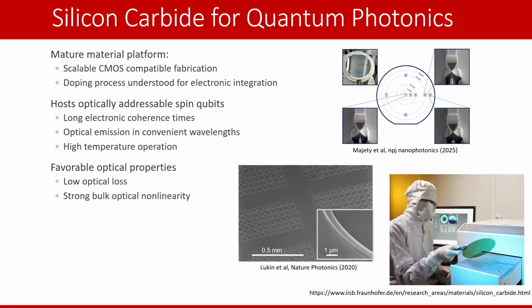And of course, silicon carbide, as a result of a lot of hard work from a lot of very intelligent people, now has excellent optical properties. It has low optical loss, on the order of less than 5 dB per meter, which is quite good, which means all of our photonics are no longer material limited. They're now nanofabrication limited. And there's also a strong bulk optical nonlinearity. I want to highlight that because it's relatively unique to silicon carbide over the other solid state platforms for cavity QED, like diamond and silicon. I suppose people are working on hBN these days too, but of these, silicon carbide is unique in that it has a strong chi-3 nonlinearity, and so this lets you access Hamiltonians that you could not reach otherwise with other materials.